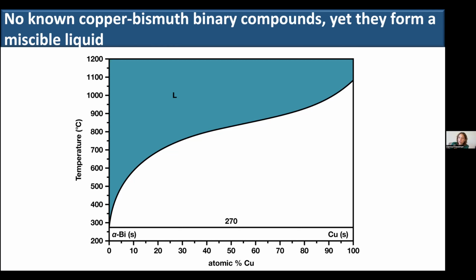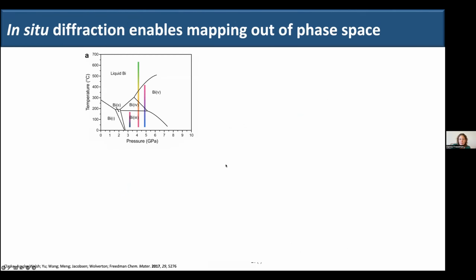And as you can see, there are no vertical lines in this diagram that would denote the existence of a phase. So, okay, we have copper bismuth. One reason that we went after it is we thought it would be easy, just what I just said. The other reason that we were excited about this is we believed that a copper bismuth binary was likely to be a superconductor and likely to have potential for additional interesting superconducting properties. So let's talk about copper bismuth. So instead of the temperature composition phase diagram that I showed previously, now we have a temperature pressure phase diagram. And what you can see, because diamond anvil cells are transformative and amazing, these cuts that we can take across the bismuth phase diagram demonstrate the temperature ranges that we were able to measure in different diamond anvil cell experiments. And so that color scheme will translate into the diffraction patterns that I'll animate in a minute.